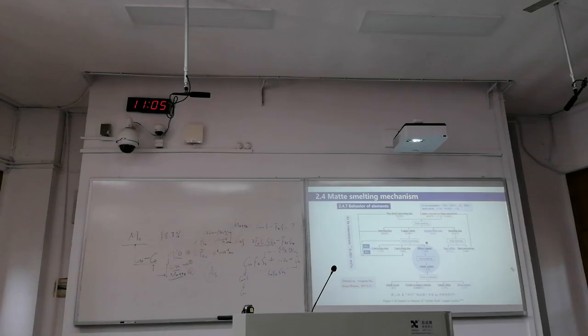So first of all, what do we have? We have copper in concentrate at 25%, and the flash smelting burners are running at 1200 degrees. So this is what we already know. Oxygen enrichment is 80, and matte grade 70. The slag iron-to-silica ratio is 1.3. So this is information we already have in our minds, right?